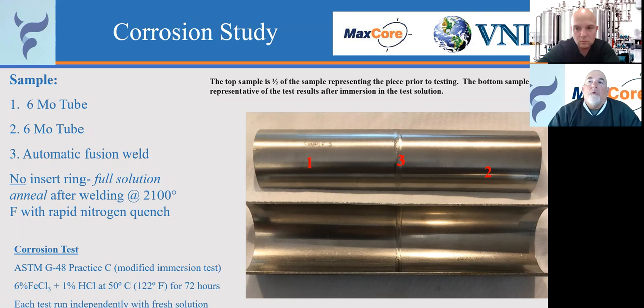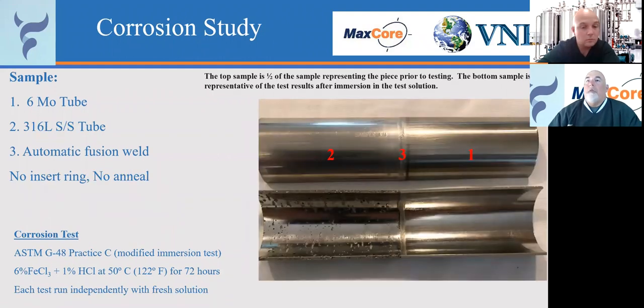When it comes to VNL, for instance, if we're going to do any type of special fabrication at our facility, in most cases we're doing small quantity product fabrication for a customer that maybe needs a one-off on a special fitting or something. Then we're going to use the weld insert ring and do that at that welding area. And then this is a 316L tube welded to a 6 moly alloy, automatic fusion weld, no insert ring, no anneal.